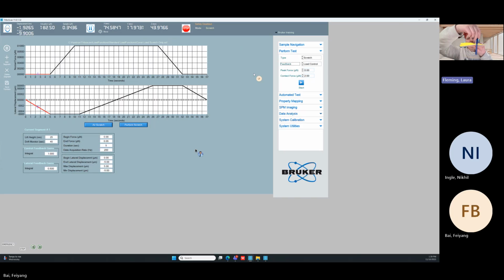However, when we begin to talk about scratch, it goes 2 microns in, and then it scratches along the sample surface and then unloads. Now, if the transducer and the sample are perfectly flat, those two numbers will be the same. But we're talking about nano indentation, things are never flat, so there's going to be some tilt. So if I do a 2 micron displacement and then scratch, I'm no longer constant inside of the sample, I'm constant inside of the transducer. People often try to use displacement control, but I do not recommend it. It is not doing what you think it is doing. So we typically recommend leaving your normal direction in load control feedback.